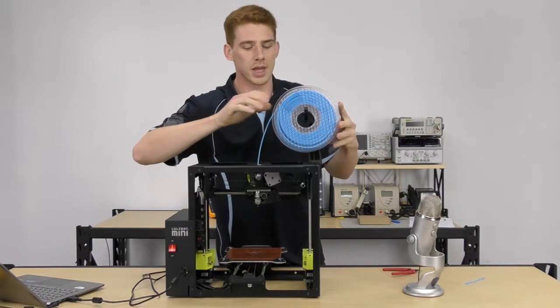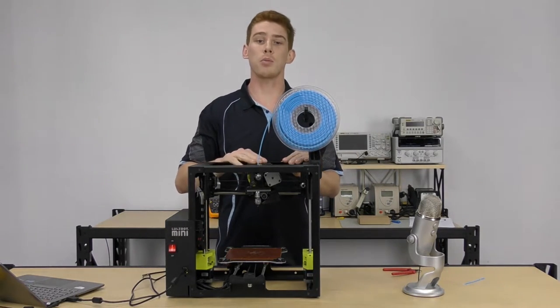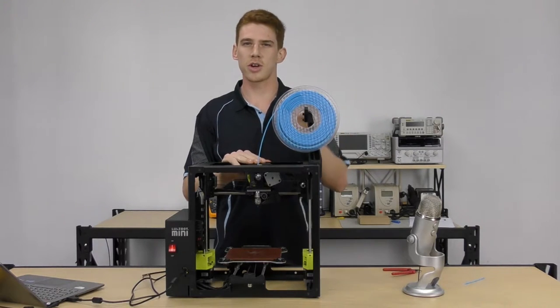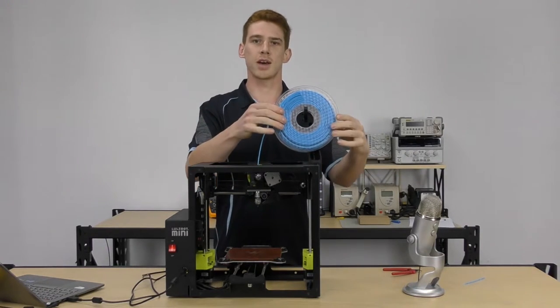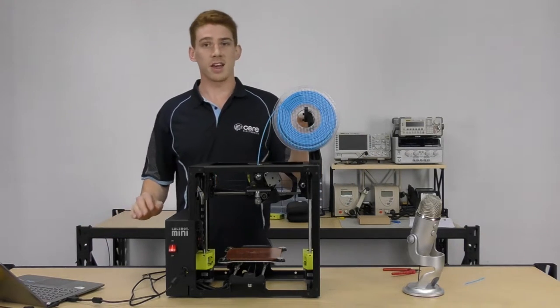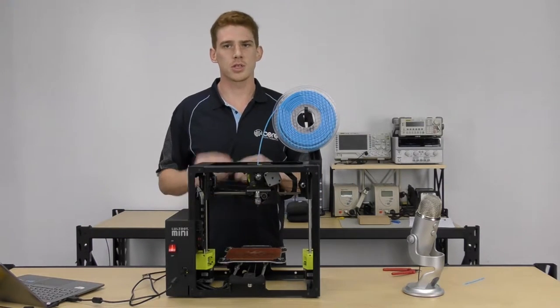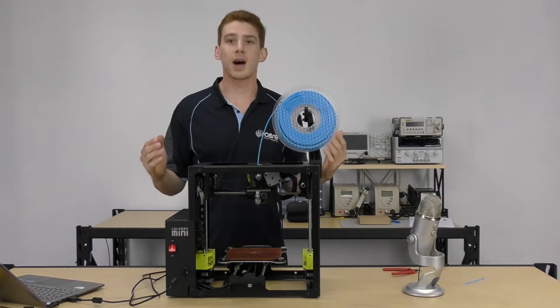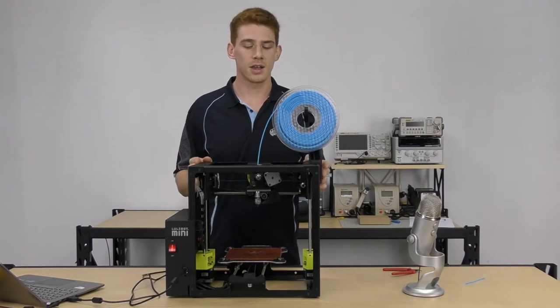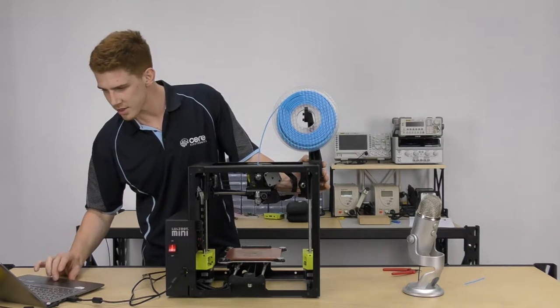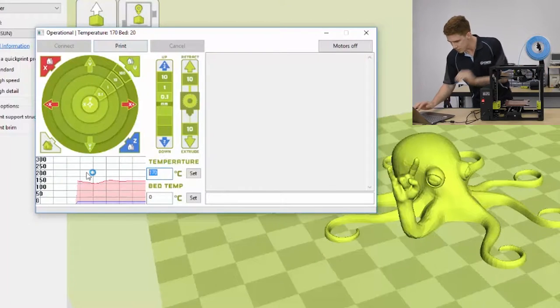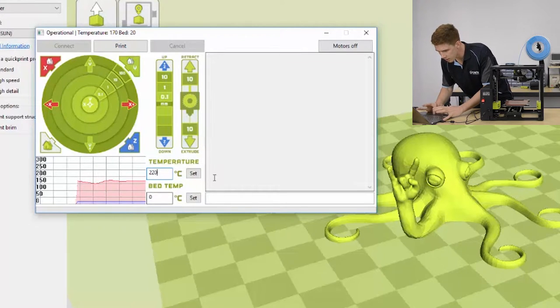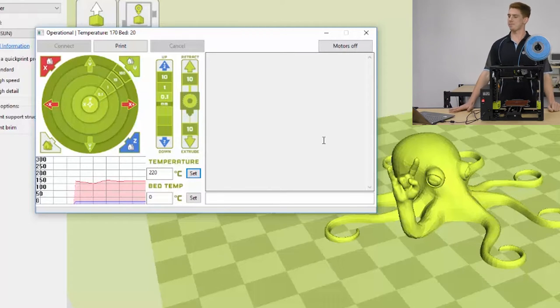So there we go. Now we're going to heat this tool head back up, and we're going to heat it up to about 220 to 230 degrees for ABS. It's labelled on our filament roll here. Once we've got it up to that temp, we're going to purge some filament through until we get a nice consistent extrusion. It's just part of the process. And then we should be right to print. So let's go ahead and do that. 220 degrees, set that temp, and we'll just wait for it to get up.